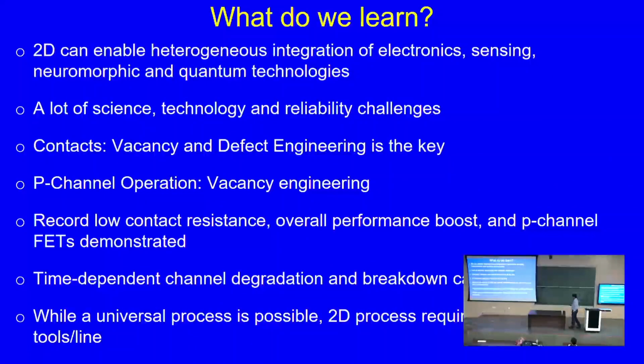Okay, so we are towards the end. Let me conclude what we learned. I talked about how 2D can enable heterogeneous integration of classical quantum systems. There are a lot of science, technology, reliability challenges, but they can be addressed. As far as the contacts are concerned, I told you that vacancy and defect engineering is the key. So you can't do conventional doping in TMDs, but you can basically create these donor acceptor states through vacancy or defect sites. P-channel operation, you can basically introduce through vacancy engineering. We demonstrated record low contact resistance, overall performance boost of these transistors, and also a p-channel transistor demonstration.